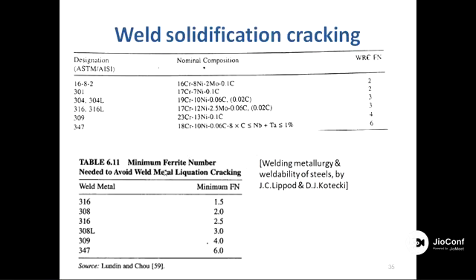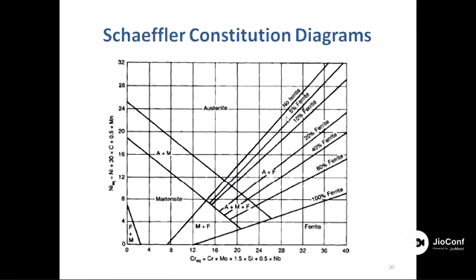So it is a minimum ferrite requirement with your weld metal of austenitic stainless steel, depending on the grade. For a higher grade like 347, you require 6% minimum ferrite number. Otherwise, for the 316, 1.5, or practically 3, is more recommended.